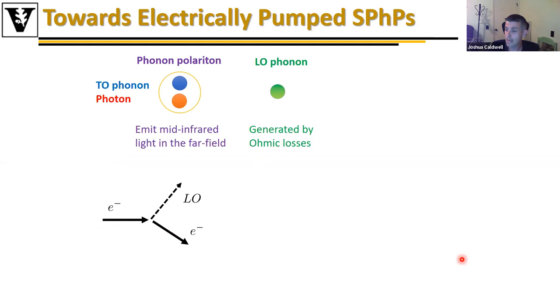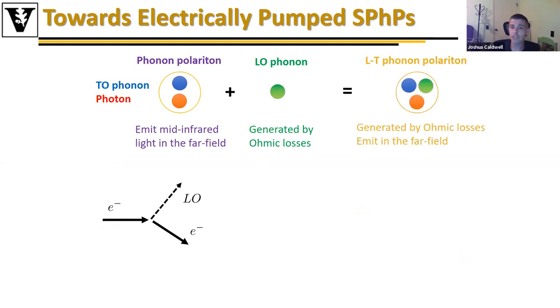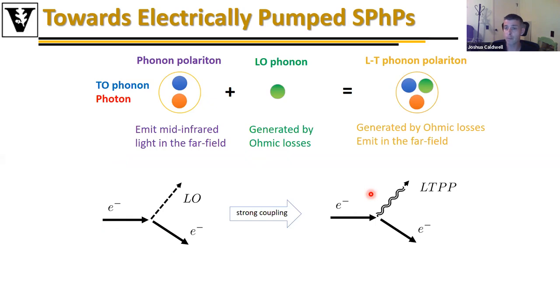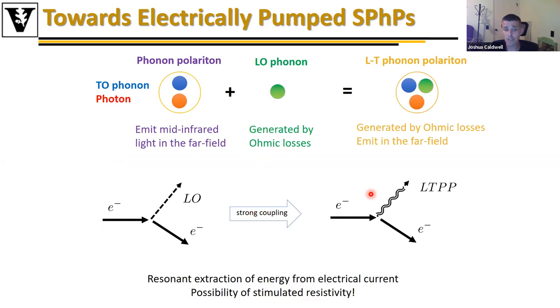process. Now, by coupling these two together, we could take the longitudinal transverse phonon polariton, this strongly coupled mode I just showed you, and now potentially have something where I could generate, through ohmic losses, an ability to make the phonon polaritons emit into the far field, providing the basis of an electrically pumped phonon polariton mode. So this is one of the other focuses that we're pushing towards now.